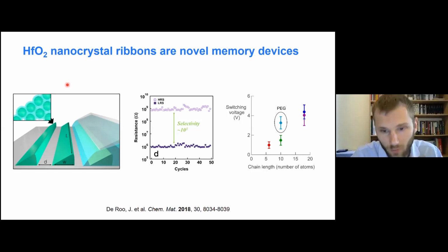And it's very important for us to keep both the voltage low, but to also keep the solution processability. And that's why those branched ligands really shine, because if you would just take hexylphosphonic acid, the particles precipitate. But if you take 2-ethylhexylphosphonic acid, the particles remain in solution, but the ligand shell did not increase. And it also allows for this low switching voltage between the two. So 2-ethylhexylphosphonic acid gives you the perfect combination of solution processability and at the same time a low switching voltage.